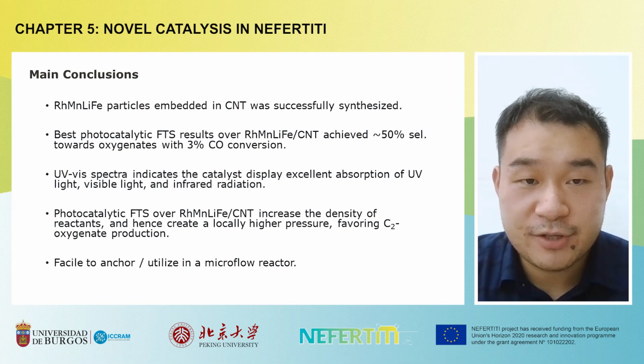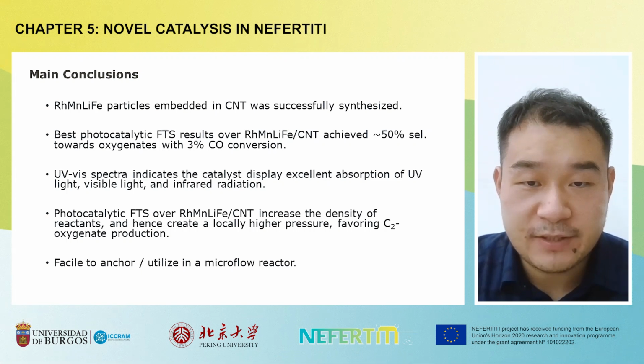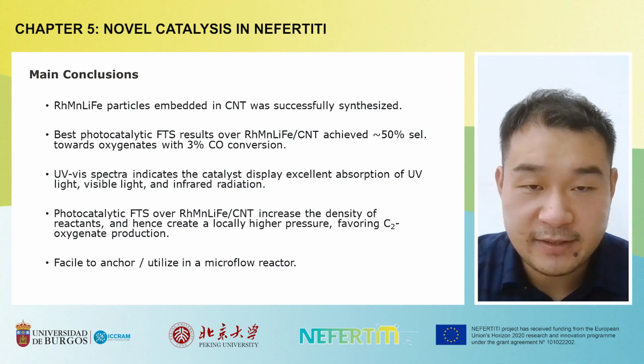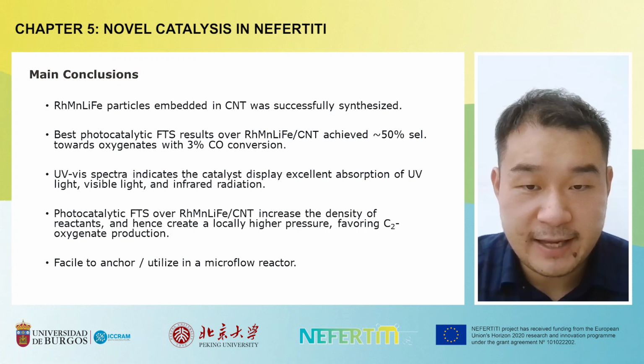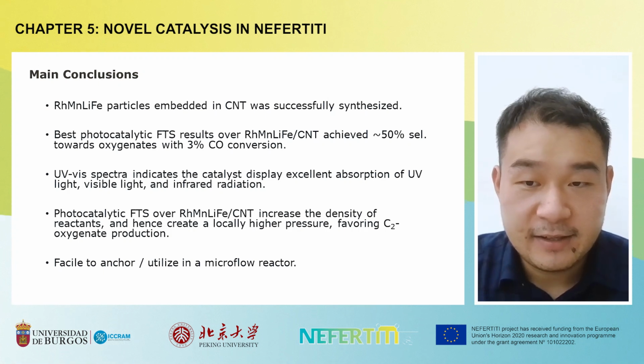And in conclusion, we prepared promoted supported rhodium-based nanoparticles embedded in carbon nanotubes, and the best photocatalytic Fischer-Tropsch synthesis results over the catalyst achieved about 50% selectivity towards oxygenates with about 3% carbon monoxide conversion. The UV-vis spectra indicate that the catalyst displays excellent absorption of UV light, visible light, and infrared radiation.